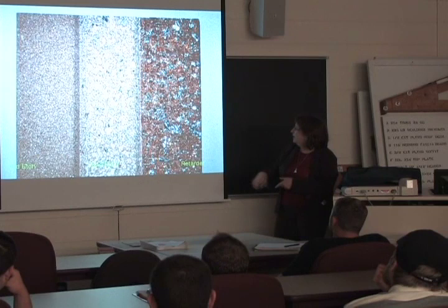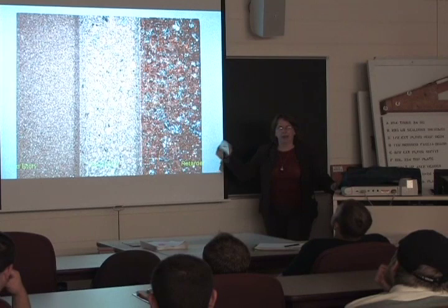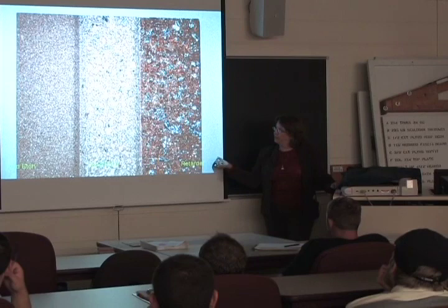In the section here, you've got a chemical retarder that's actually a sugar-based retarder that stops the concrete from curing on the surface. So you stop the concrete from curing, you then use a high-pressure water wash, and you can expose a lot of the aggregate that way. So you really can get very different looks. It's all the exact same mix of concrete. What they've changed is the way they finished it.